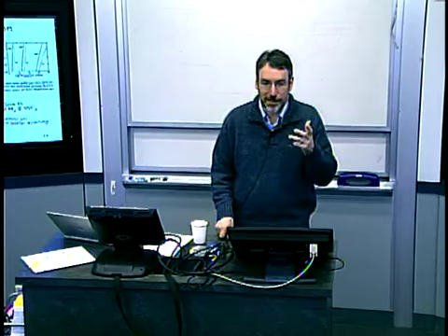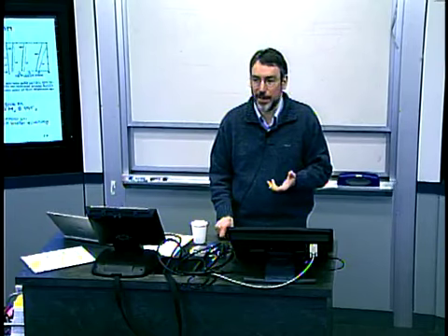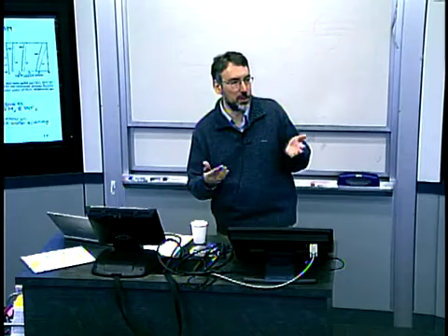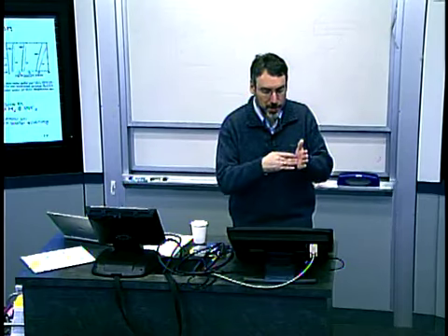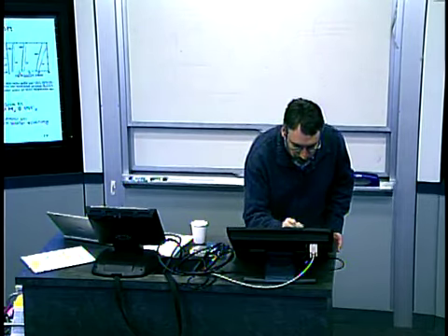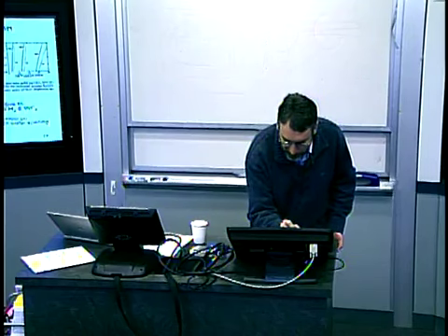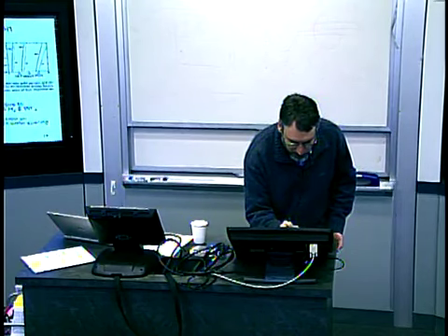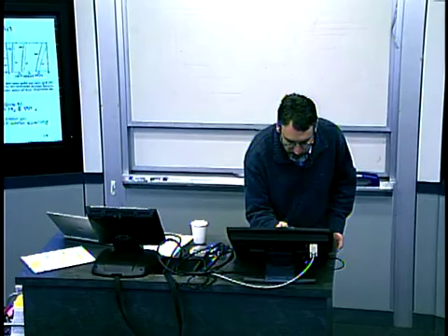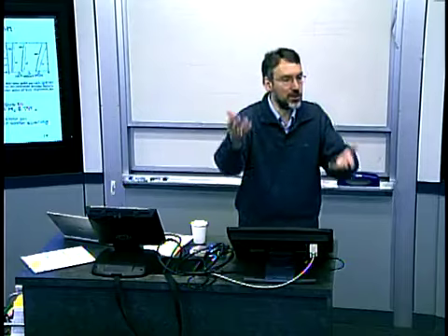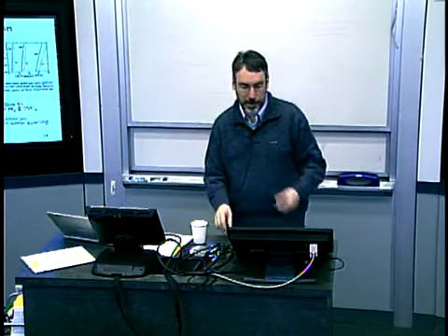So they would plot, realize they've got 4 inputs and 7 outputs. A 4-dimensional input space is very hard to visualize. So what you resort to are typically 2-dimensional plots where you might plot 1 output or 2 outputs as a contour. So in this particular plot, the solid line, I believe, is growth rate. And the dashed line here is WF6 conversion. And you can start to get a feel for, as for example, the WF6 pressure and the temperature change, what trends you get in those 2 parameters and what trade-offs you get in those 2 parameters.